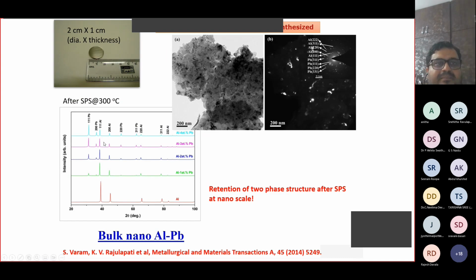And then when we compacted this powder processing at 300 degrees centigrade, we got a disc like this. The microstructure is like this. This is a bright field image. This is a corresponding dark field image. And this is the diffraction pattern. By indexing it, it shows that we have the presence of both aluminum and lead. And even after exposing to 300 degrees centigrade, you could retain the same two-phase structure.